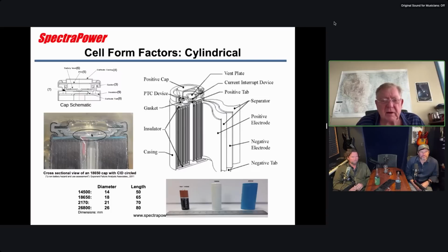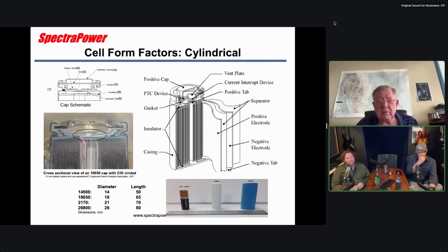The contact from the outside is spot welded to the tab on the jelly roll. The reason it's done that way is that the failure symptom for lithium-ion is that it will generate a lot of gas. It'll pressurize this can, and when it does that, it pops this. It acts like a permanent fuse, because it'll break the weld, and your cell will be disconnected completely and permanently. That's cool.